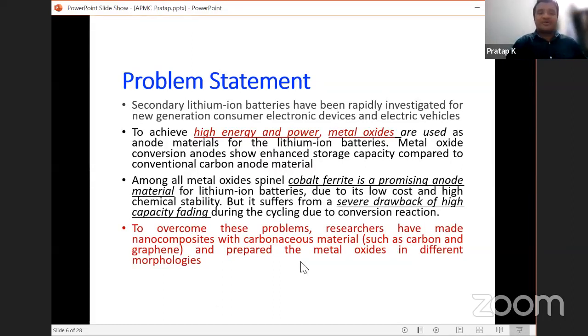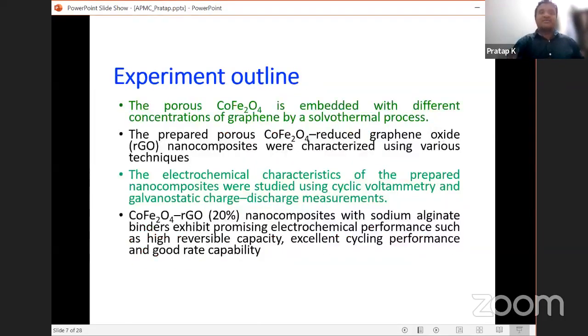Capacity fading is because of the conversion reactions. To overcome these problems, researchers have made composites with carbonaceous materials, meaning graphene and metal oxides mixed together. Then capacity fading might be decreased. So here we are studying cobalt ferrite and cobalt ferrite mixed with reduced graphene oxide. We want to check how reduced graphene oxide with cobalt ferrite mixed together will work as an anode for lithium ion batteries.